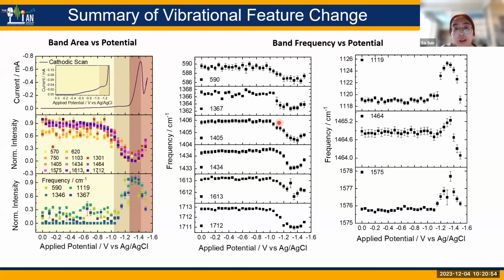Meanwhile, we can also see for this group of peaks, they have a constant frequency and then a redshift of frequency and then recovery during the first reduction and second reduction. We think this is really interesting and we can dig more into it. So here I just mark the peaks which have redshift by the red rectangle and blue shift with the other.